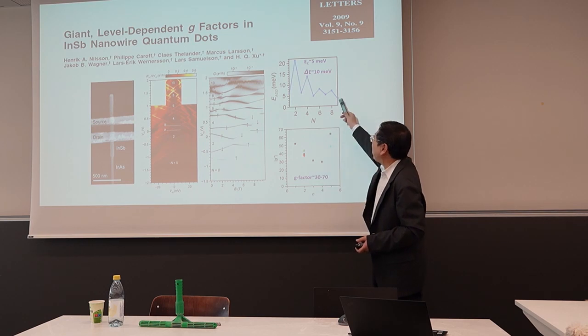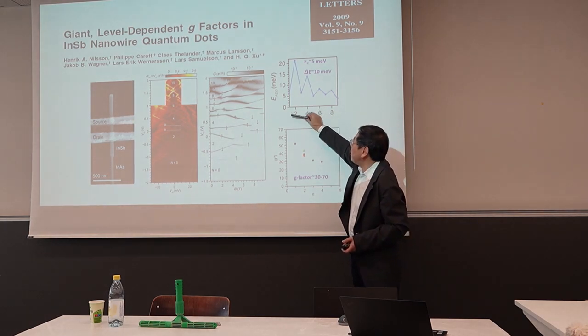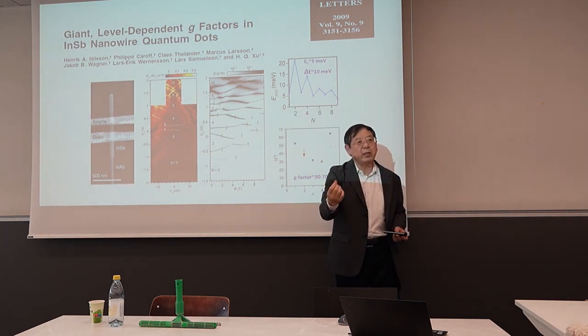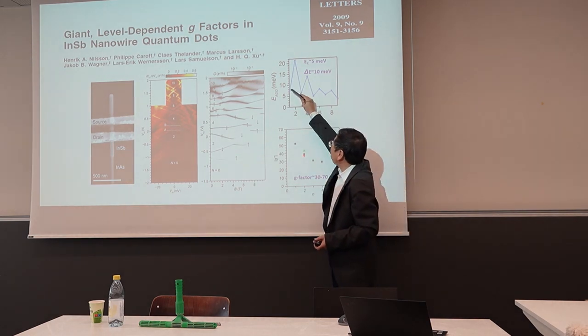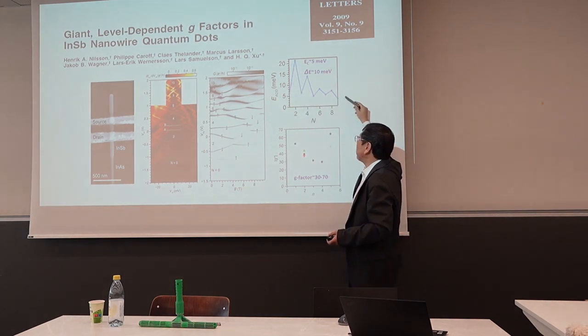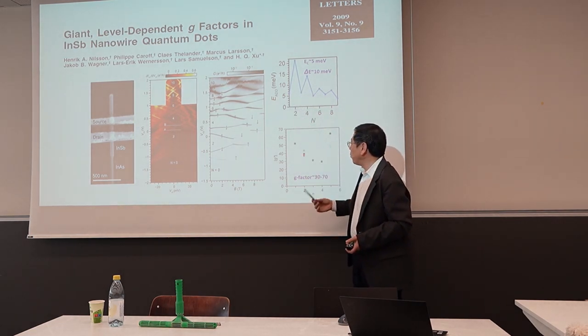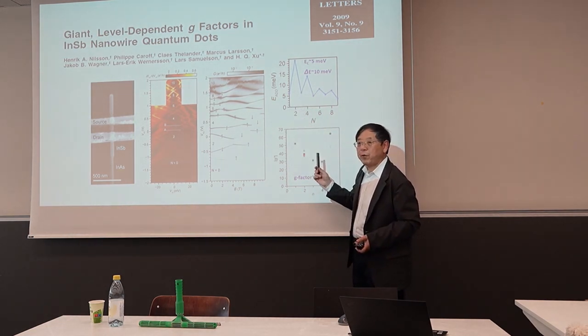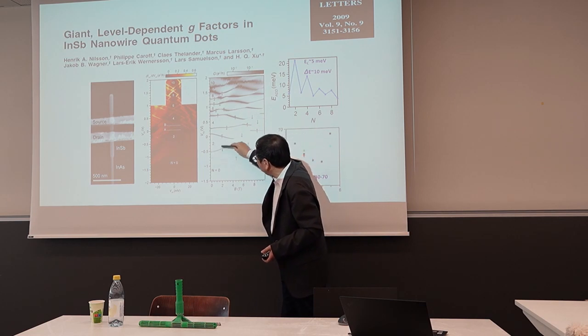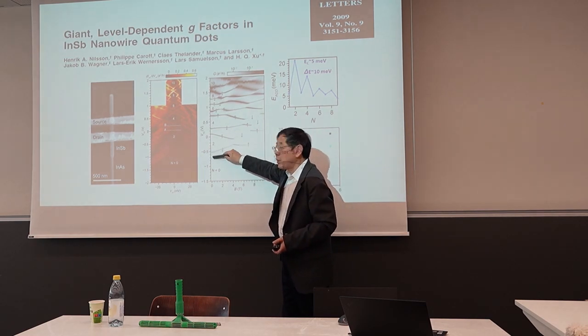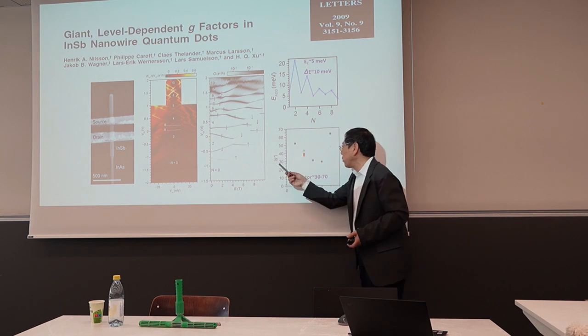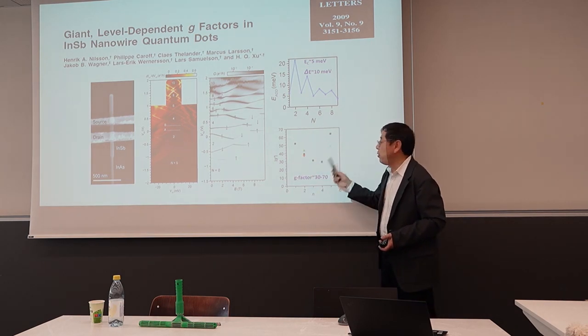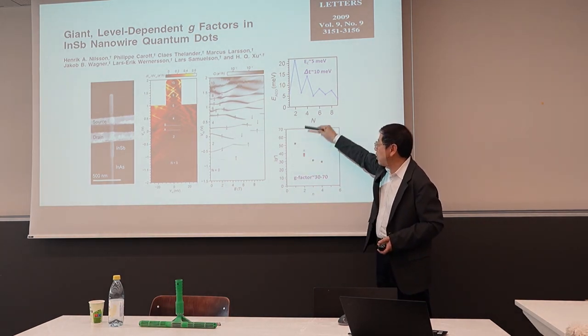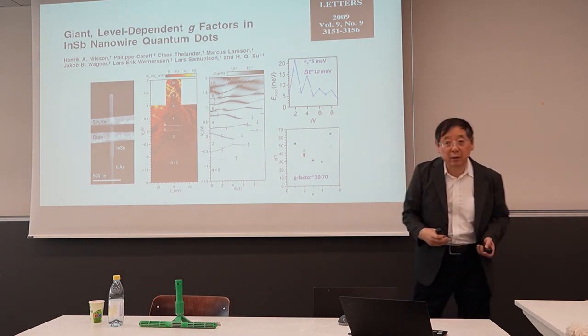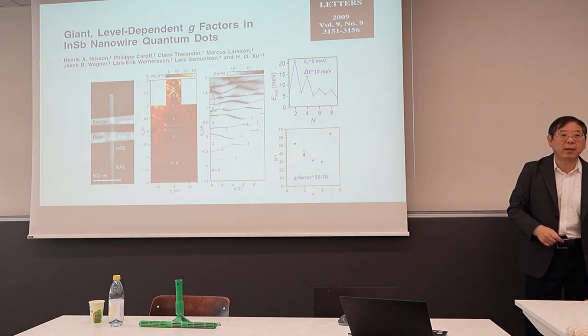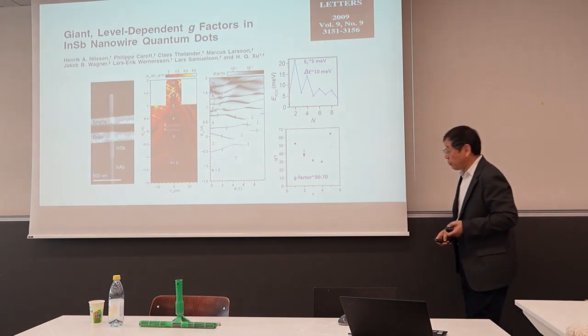With this one, you can map out the charging energy. And this we call the addition energy, meaning the charging energy plus the confinement energy. If you subtract the background, what is left over is the charging energy. So really you can see that. And also from this splitting, moving up and subtracting this charging energy, you can get the g-factor. These materials, at different levels, have different g-factors, around 30 to 50 or 70. It's a very large g-factor. This indium material is a very nice material to do quantum devices.